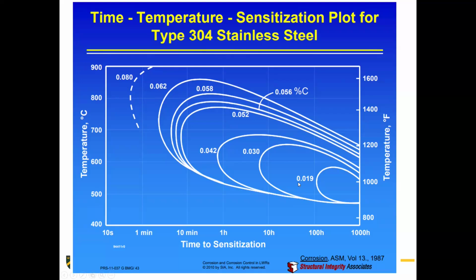Let's look at our most extreme case, 0.019% carbon, very, very low. To actually get sensitization to happen in this case, you have to hold it for about 100 hours in a fairly narrow band, right around 500, 600-ish. That's obviously not realistic. Even if you're welding something, it's going to cool out of that range. It's either going to be above it or below it way longer than 100 hours, so you're ostensibly not going to sensitize it. But on the flip side, if you add a lot of carbon, you become very, very susceptible. The ranges are much shorter, down to like a minute in some cases, and very susceptible to forming those carbides.